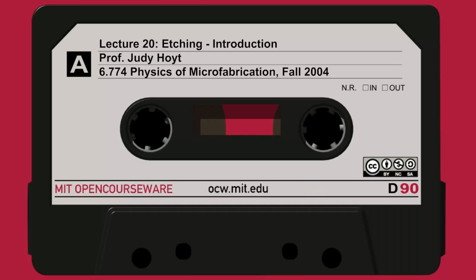So this anisotropy factor is 0 if you're isotropic etching, because then B equals D, or R lateral equals R vertical, and then A f goes to 0. If you're totally anisotropic, B goes to 0, because you don't etch laterally at all, and this number goes to 1.